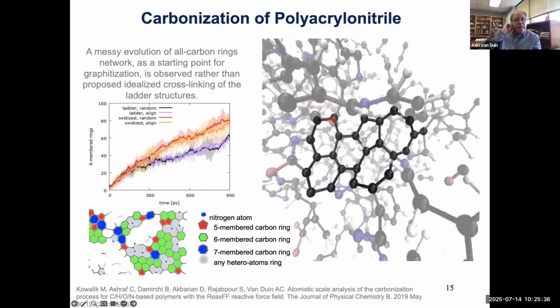We can, for example, now see how a random structure changes from a ladder structure. In our ReaxFF simulation, we can also see how oxidation changes these kinetics. And we can follow, as a function of time, the type of rings that we form. And we see indeed that we form a backbone of 6-membered rings, the green curves over here. But at the edges, we see many defects show up, especially 5-7 defects and other types of heteroatoms, where there's still some nitrogen remaining in there. So the process is rather complicated.